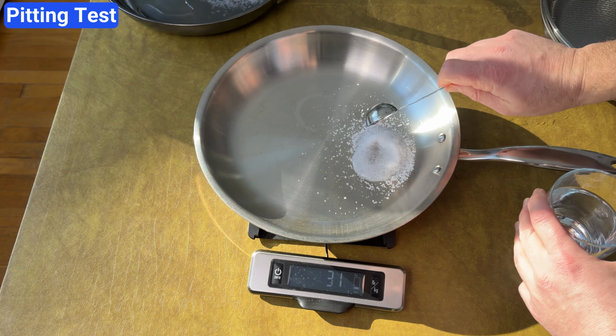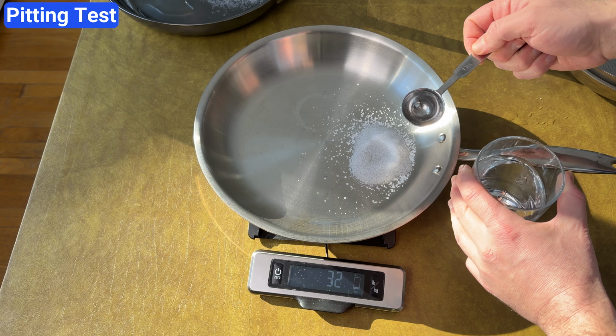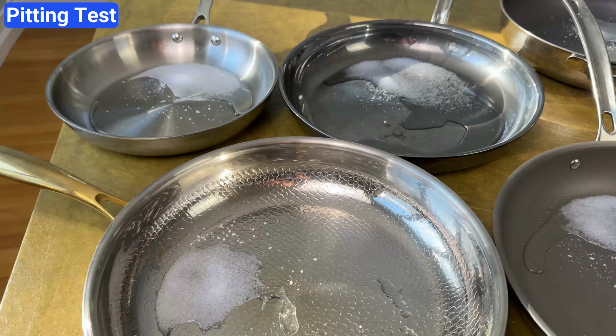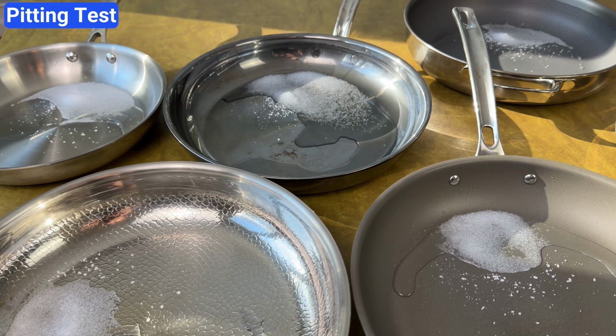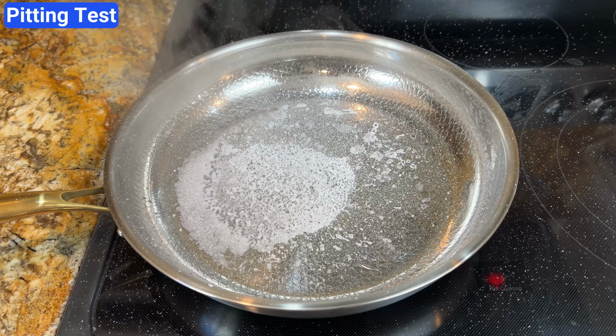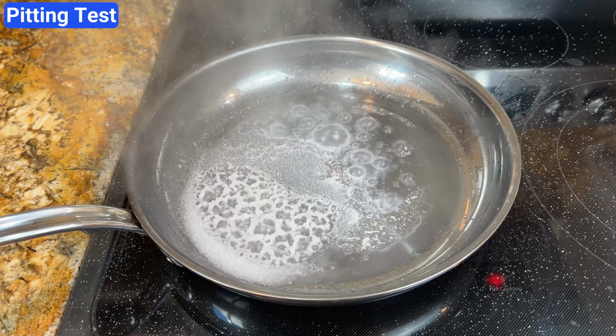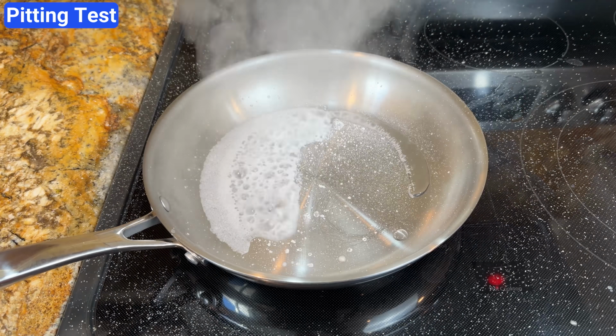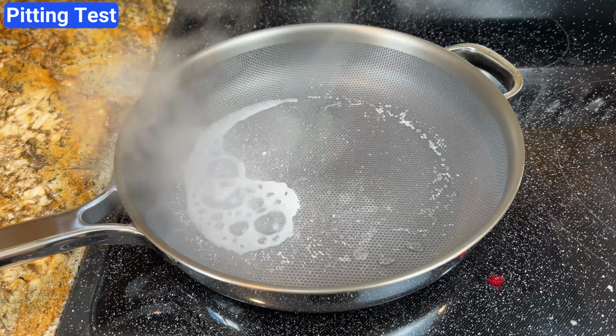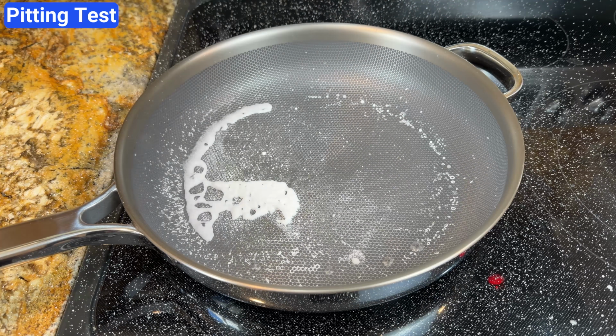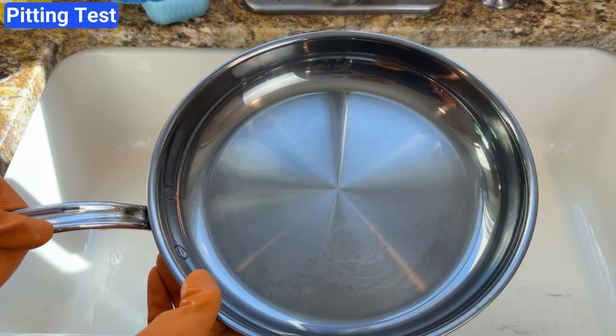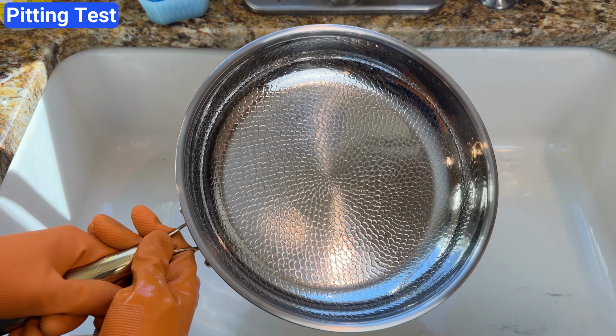I added 20 grams of non-iodized salt and 20 grams of filtered water to each pan and let them sit for an hour. Then I put them on the burner on high until the water evaporated. Then I let them sit for another hour before washing and inspecting. I did 3 rounds of this with each pan. After the first round, all 5 titanium pans looked completely fine.